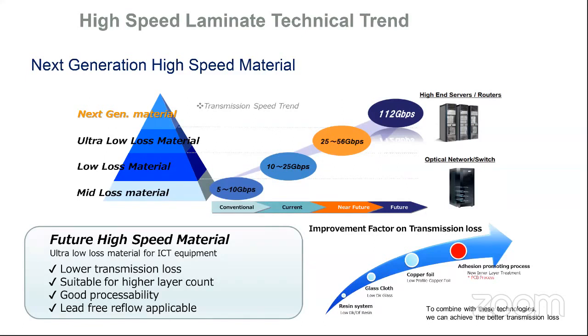There's one thing developing glass and resin systems, but it has to be manufacturable as well. Can you drill it? Can you plate it? Will it survive multiple lamination cycles? And as boards get thicker and more dense, they need to have lead-free reflow compatibility. I'm preaching to the choir here, but boards go through numerous reflow exposures. And so the package needs to be able to withstand the kinds of z-axis expansion that boards will see under these multiple thermal excursions.